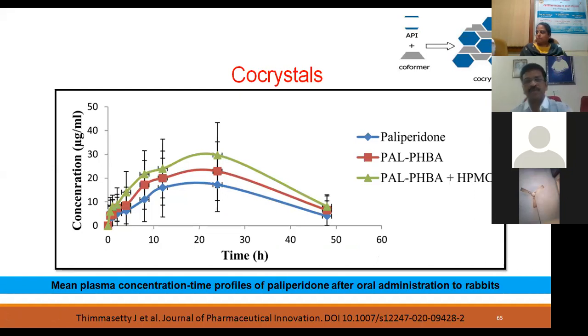We finally took up the work and worked on paliperidone. This example is our research work. We selected the excipients, we selected the co-formers, and we prepared the co-crystals. Again, here we applied the knowledge of the solubility parameter. We calculated the solubility parameter of the drug and also the solubility parameter of the co-former. And when they are very near to one another, then better co-crystals form, which was evidenced in the reports.